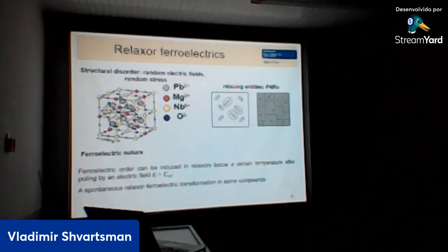So, when we have this relaxor ferroelectric material, what do we need? We need structural disorder. The typical example is lead magnesium niobate, a material with the so-called perovskite structure. Perovskite is a system of octahedra. In the middle of the oxygen octahedra is one of the transition elements.